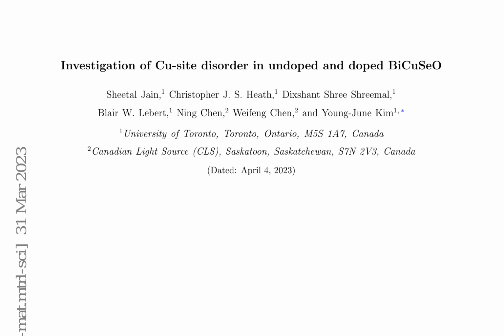Due to the relatively low concentration of Ag, transmission geometry was not suitable, and Ag K-edge EXAFS measurements were performed in a 90-degree fluorescence geometry using a 13-element Ge solid-state detector. Cu K-edge EXAFS data, on the other hand, was collected in both transmission and fluorescence geometry simultaneously. Standard Ag and Cu foils were used for energy calibration, respectively.